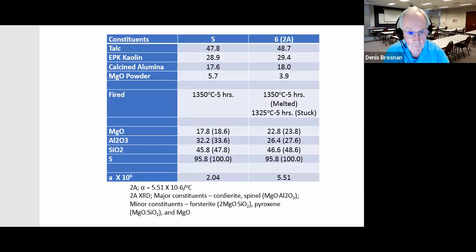Now, I did this over a number of years, and we came up with various talc, clay, kaolin mixes. Sometimes we used MgO powder in some of the mixes with some kaolin, trying to meet the composition on the money. We fired the composition up to about 1350. In some cases, we melted the compositions. We got thermal expansion coefficients down here as low as 2 in the direction that we were making the samples, trying to align the clay particles.